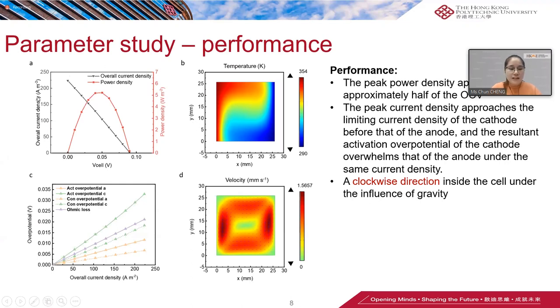As shown in figure A, the peak power density appears at approximately half of the OCV. Figure B shows the temperature distribution in the electrolyte. According to the electrode kinetics, the temperature-dependent rate constant at the low temperature electrode is lower than that of the higher temperature electrode. Thus, the theoretical exchange current density at the low temperature electrode is lower than that at the higher temperature electrode.